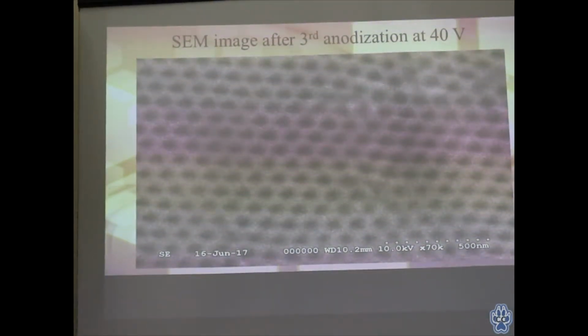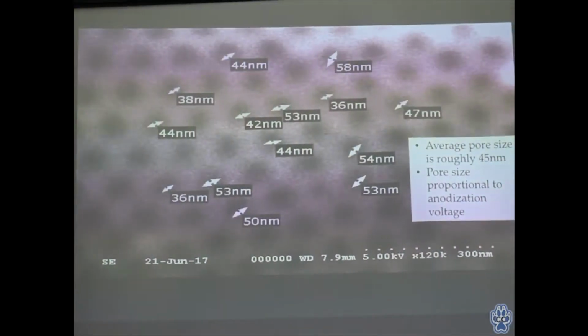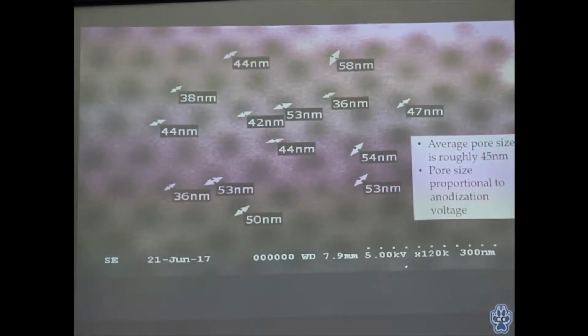This is an SEM image of one of these samples after a third anodization at 40 volts. As you can see, these pores are highly ordered both vertically and horizontally, and this is basically exactly what you would be looking for. Again, this is the same sample except much closer at a much better scale, and we were able to measure the diameters of these pores roughly, and we were able to calculate that the average pore size is 45 nanometers, which indicates to us that the pore size is proportional to the anodization voltage.